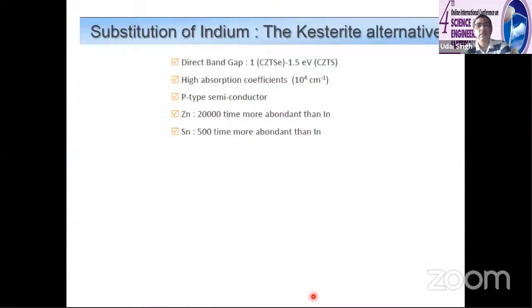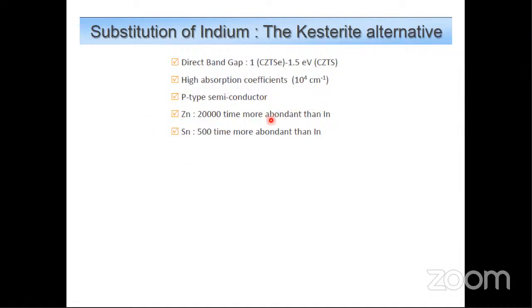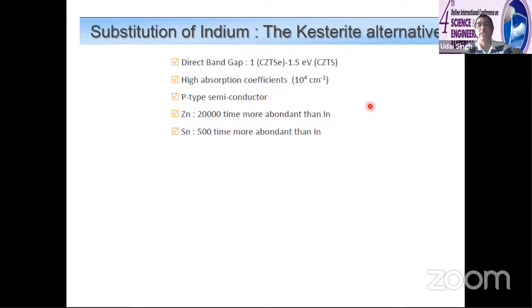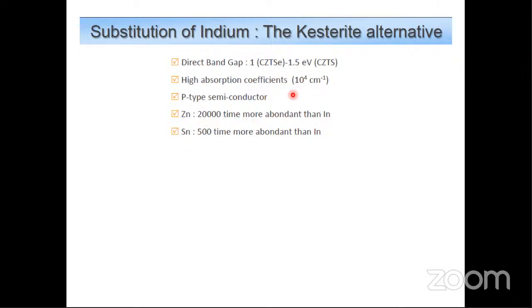Some of the applications. There is a certain problem with copper indium: if you go for gigawatt or terawatt, then the scarcity of indium is there. So people try to replace some of the indium and gallium. People have come up with copper zinc tin sulfide or copper zinc tin selenide. It's again a high absorption coefficient, p-type semiconductor. Zinc is 20,000 times more abundant than indium. Tin is also abundant. So these are earth-abundant and non-toxic materials.